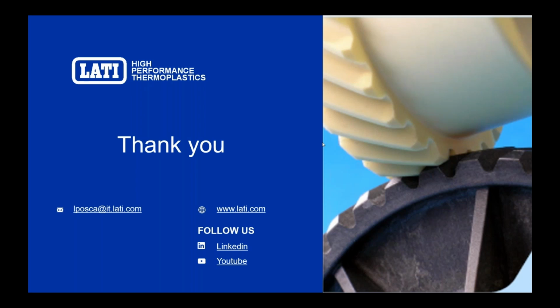Ultra high molecular weight polyethylene has shown to be very difficult to disperse above 300 degrees C. So I would say PPS is already close to borderline. But to answer your question, I would say polyamide 9T or PPS with ultra high molecular weight polyethylene, or why not polyamide 4,6. LATI is not compounding polyamide 4,6. DSM is doing this job, but I would say polyamide 4,6 with ultra high molecular weight polyethylene could be a very interesting solution. Okay, now our time is over.